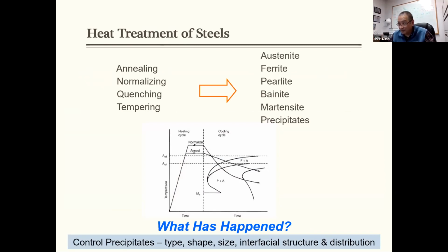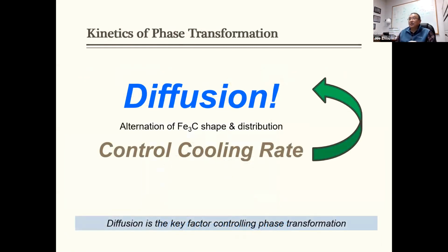Okay, I'm going to jump through this. The key on the heat treatment or on the phase transformation is the diffusion. So what people try to do is control the cooling rate for a given steel, to change the precipitate shapes and the distribution. So the diffusion is the key. If you want to heat treat this steel correctly, you have to allow the diffusion to occur at a given temperature for sufficient time.